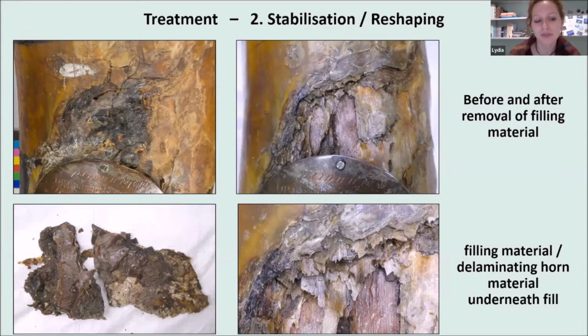I carefully removed the fill and discovered that the fill was covering up a hole in the horn. Further on, the horn material degraded in the contact areas to the filling material, which reconfirmed the necessity to remove the fill. The horn had delaminated into very thin and brittle layers that actually reminded me more of filo pastry than of horn material, as you can see here in the lower image. Additionally, filling material had settled in between the delaminating layers and had driven them further apart.